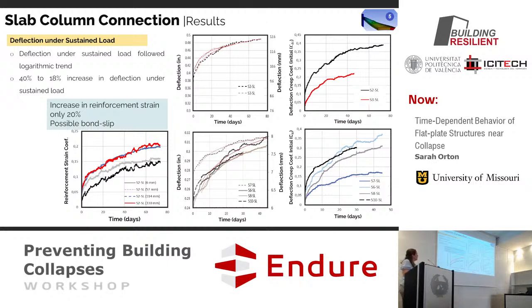The deflection under sustained load followed pretty much a logarithmic trend, the same behavior that you saw in the bond and the cylinder tests. Initially, a lot of deflection, and then it tapers off with time. And you got about a 40% to 18% increase in deflection under sustained load. Whatever it did initially, about 40% more deflection under the sustained loading period. But interestingly, the strain that we had in our reinforcement increased only about 20%. So even though the specimen was deflecting about 40% more, the strain in the reinforcement was only picking up about 20% more strain. And I think that is due to some bond slip, some slip in the structure, allowing it to redistribute the loads, and not all the load that the concrete's losing is going into strain in the reinforcement.